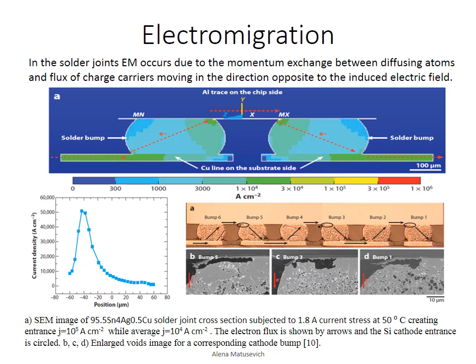This figure shows a scanning electron microscope image of SAC alloy, subjected to 1.8 ampere current, stressed at 50 Celsius. As seen from the picture, void formation due to electromigration occurs only at the cathode end of the chip side, causing failure in only one of the two solder joints, not in every joint.